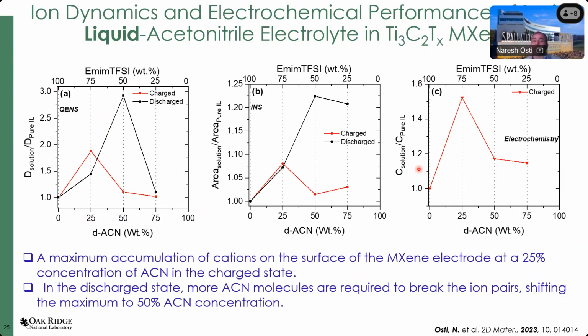But more conclusive information we can get if we plot the normalized diffusion coefficient as a function of the acetonitrile concentration. As you can see, the normalized diffusion coefficient is at its maximum once you have 25% acetonitrile in the system, and that maximum shifts to 50% in the discharge system. What does it mean? There is a particular concentration at which the maximum number of ions get attached to the surface of the electrode.